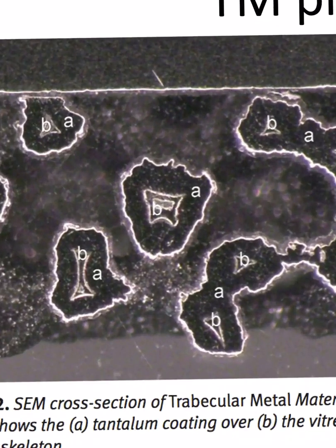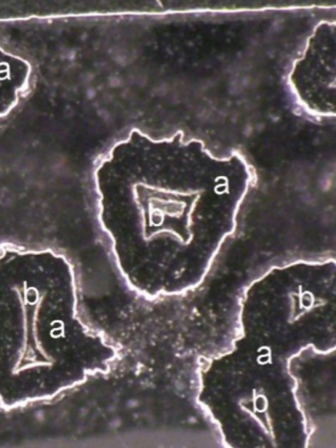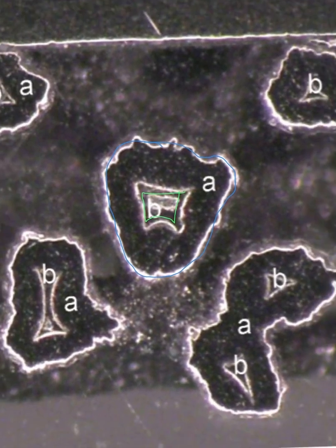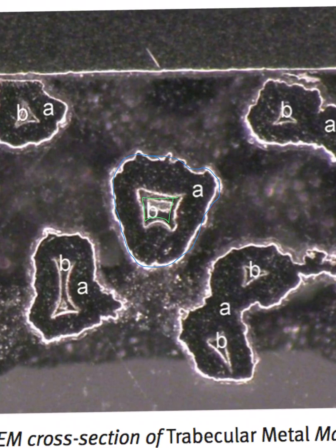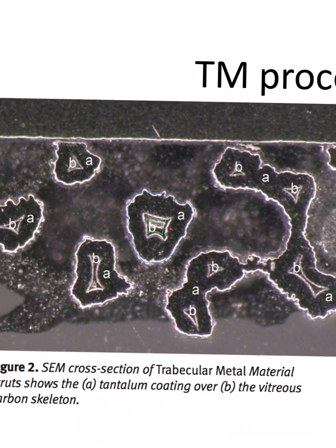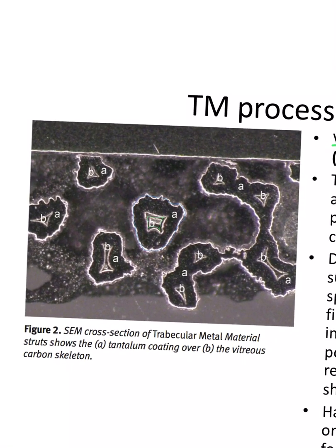And so this is zooming in here. You see this B phase is your vitreous carbon, and then the A phase on the outside of it is the tantalum, dense tantalum, by the way, sitting on the outside of that carbon skeleton. All right. So you make this preform. Again, a lot of organic sponges, you just heat them up. They make a very delicate carbon structure, and then you take that very delicate structure and you coat it with tantalum. Does everyone see that? That's what all that is.